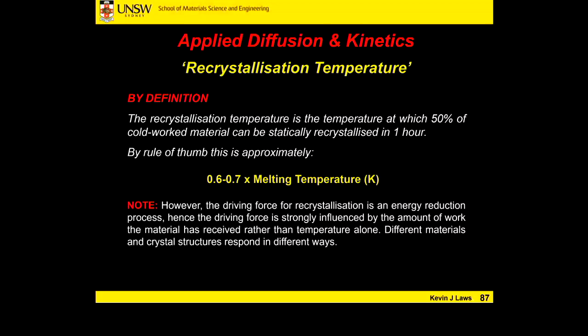So hopefully we're starting to appreciate that the kinetics of recrystallization depends on a few things: how much pre-existing deformation there is, the temperature we're holding our material at, and then the time as a consequence.